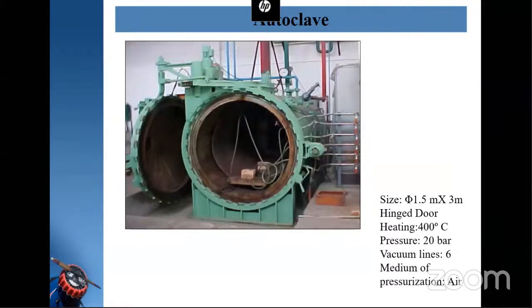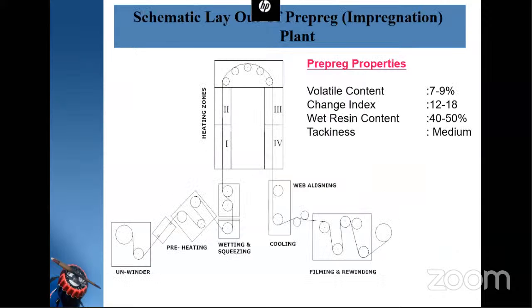So here you can see the actual equipment which is installed in our laboratory. It is around 1.5 m diameter and 3 meters long, with a door mechanism like a pressure cooker concept. The door is designed so that we can heat the component up to 400 degrees centigrade, and we can apply pressure around 20 bar, and vacuum lines are given for extracting the volatiles from the component during pressurization. 6 vacuum lines are available, and we can apply maximum 1 bar negative pressure in the component.